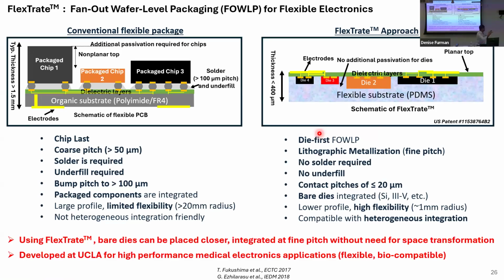So, quickly, I'll talk about how the flex trade approach to flexible packaging differs from the conventional approach. In the conventional approach, you usually use a thinned organic substrate with some metallization on top, and then you flip chip attach the packaged components with some kind of solder. But in the flex trade approach, you just embed the dies in the PDMS and then you fabricate the wiring on top of that. There are many advantages of the flex trade versus the conventional approach. In the conventional approach, you have coarse interconnect pitches greater than 50 microns, but in flex trade, you lithographically define them so that you can go to very fine interconnect pitches. And here solder is required, underfill is required, but no solder or underfill is required in the case of the flex trade process.